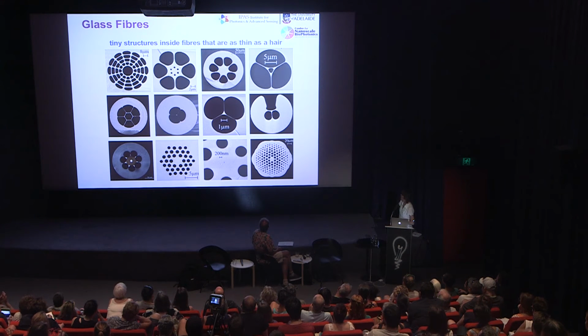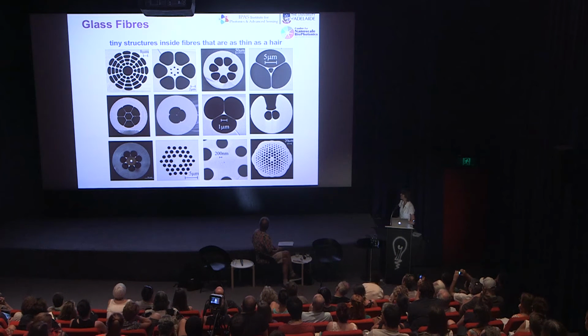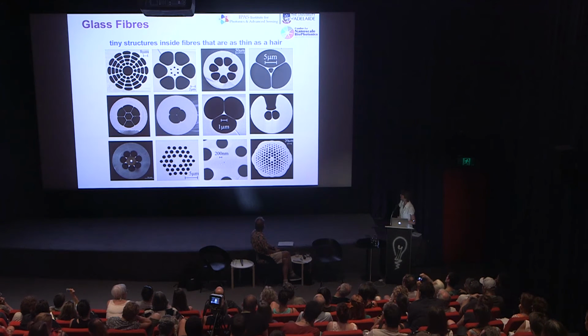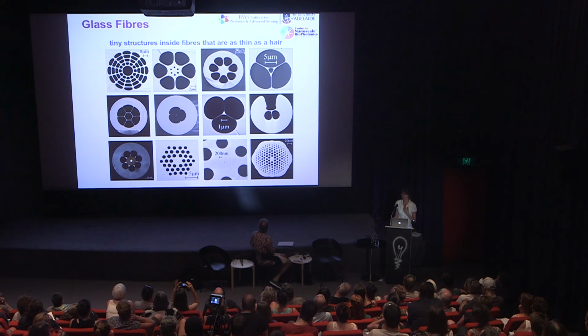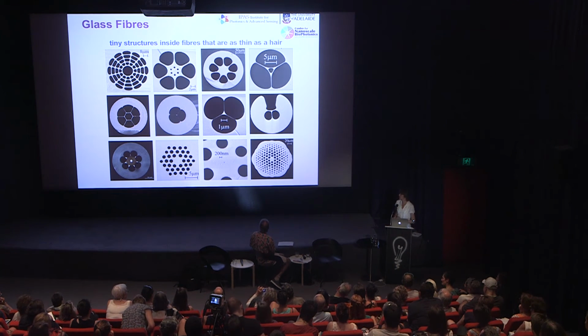Here you see a few examples of the fiber structures we make. So we can preserve the holes that are in the preforms in the fibers. Now all these images are electron microscope images, which is a very nice continuation to the previous talk. And here now the scales are quite different. Some of these structures are just visible in an optical microscope. But some of these structures, you have a hole with 20 nanometer in diameter, so really an electron microscope is required to see them.